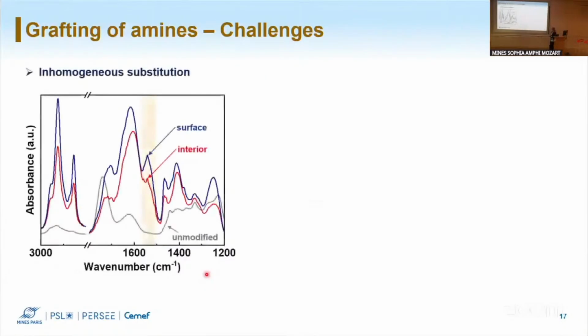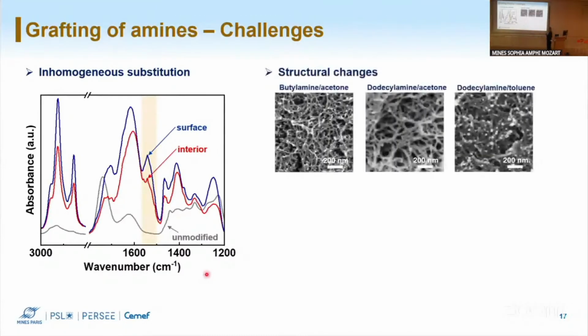However, we had a lot of challenges with this work, which is good and bad. So first, we noticed that the substitution was not homogeneous. This we saw with FTIR. So we had a higher substitution on the surface of our aerogel and lower as we were going inside the material. Then we saw that we had some structural changes at the end.